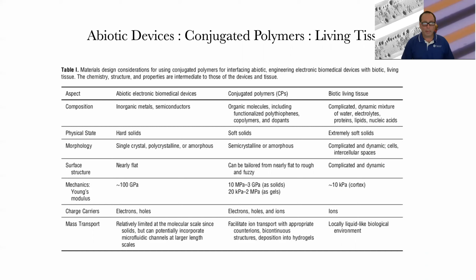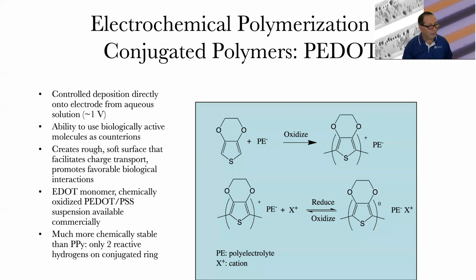So very interesting because of that. Now, as I mentioned, the polymer that has received a lot of attention is this chemically stable polythiophene called PEDOT. PEDOT is available commercially from Heraeus. They bought the technology originally developed from Bayer. And commercially, it's sold as a suspension, so you get it in a bottle and you can cast it as a film. My colleagues in France add a cross-linking agent called GOPS that creates a stable film that then won't redissolve when it's implanted into the body.